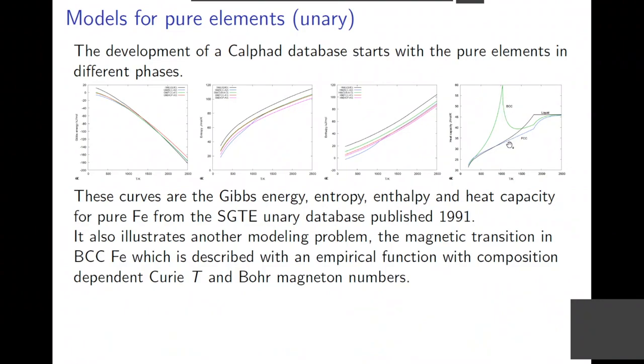Iron has a magnetic transformation in the BCC phase, but there is no magnetic transition in FCC except at very low temperature, around 70 Kelvin. And basic CalPhad has only dealt with properties above 300 Kelvin, because that's where you have some kinetically-controlled transformations. Below 300 Kelvin, there has been no interest in CalPhad techniques until recently, when people started doing ab initio calculations.